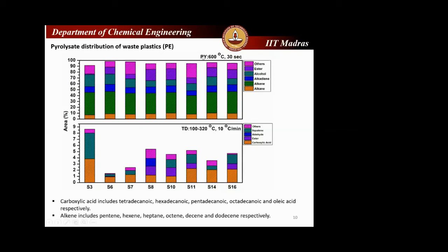And if you look at the pyrogram, which was carried out at 600 degrees centigrade, the alkane percentage is higher. Because these are made up of polythene, the pyrolysis happened due to thermal cracking, like the end-chain scission mechanism. Besides all these markers and the alkane and alkadiene triplets, I also got some alcohols and esters. These are due to the presence of some oxygen, might be due to oxidation of hydrocarbons, so these compounds were formed in the pyrogram.